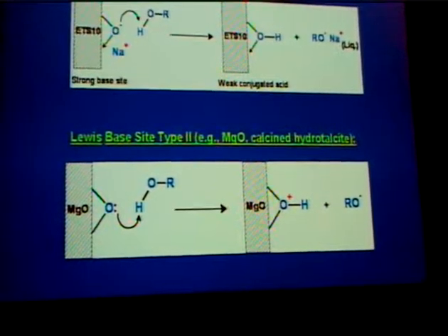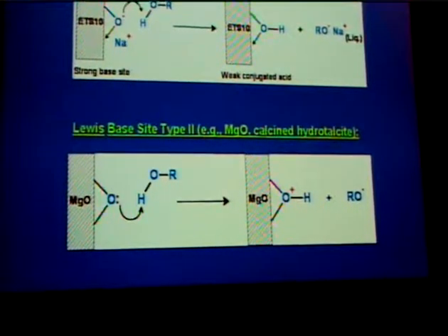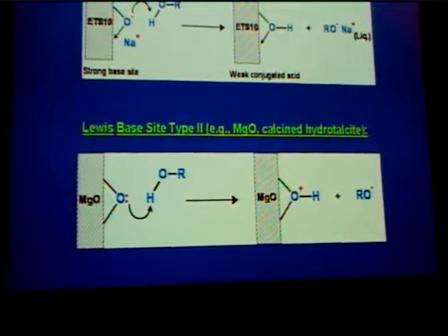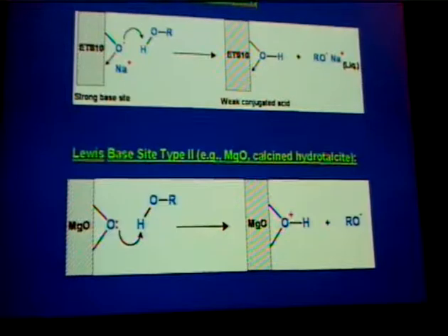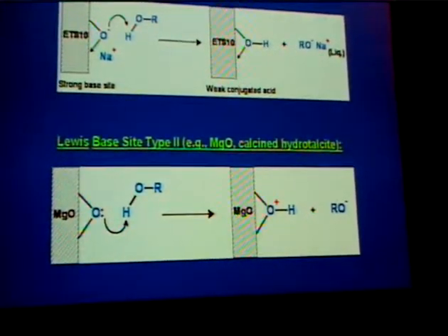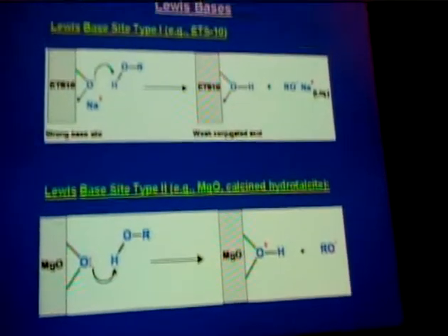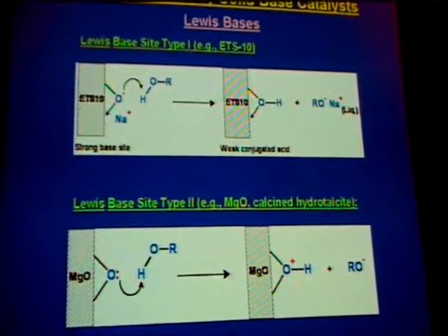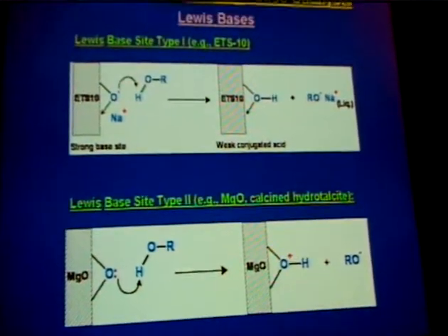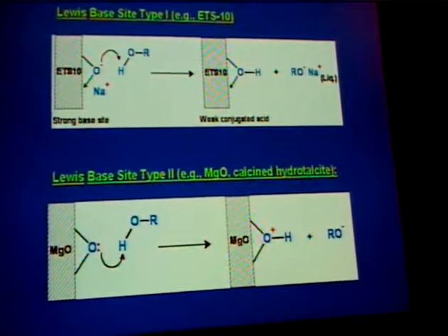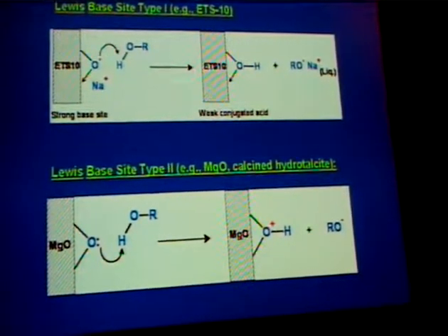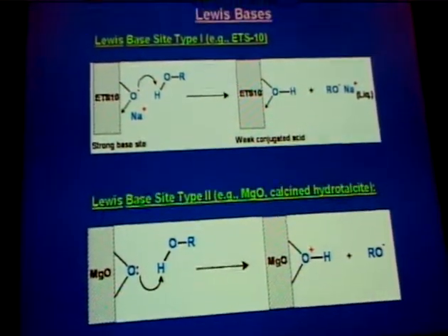And for these catalysts, there may be different mechanisms for this to happen, but the most straightforward mechanism is if you have the active species on this catalyst taking a proton from the alcohol, forming an alkoxide, and then this alkoxide will be able to carry out the reaction, and it won't leach because you always will have this counter ion attached to the surface. So when you're thinking about designing a catalyst, you have to make sure this happens, that the counter ion stays back, so this species won't leach and you will have a reusable catalyst.